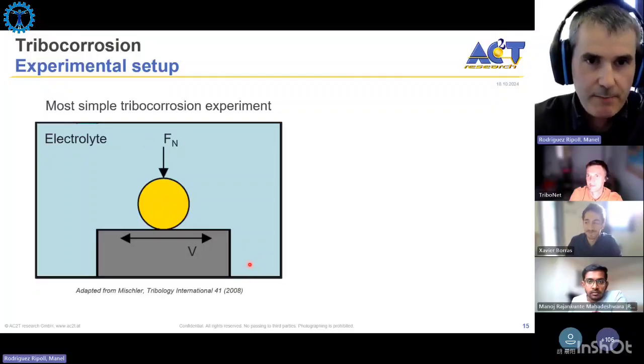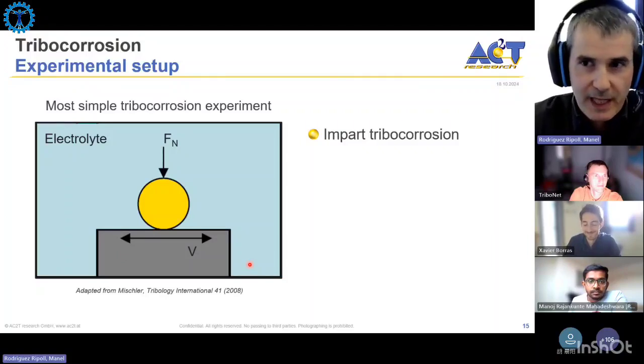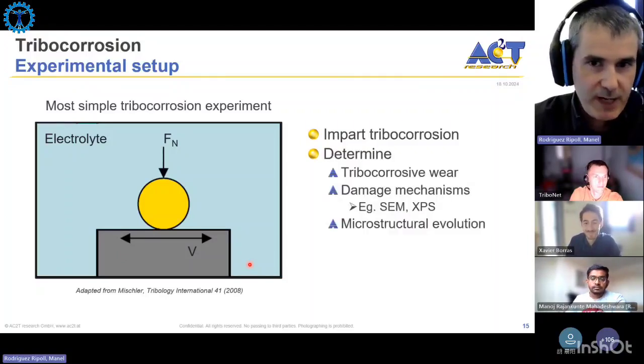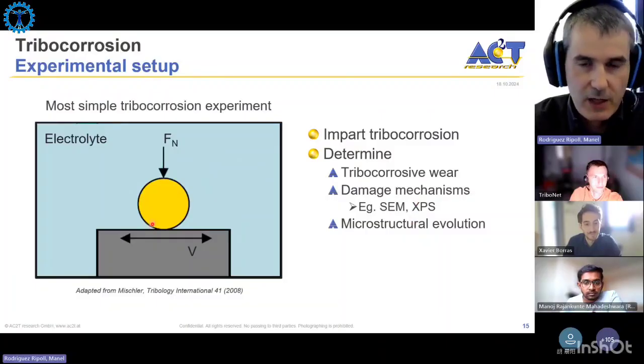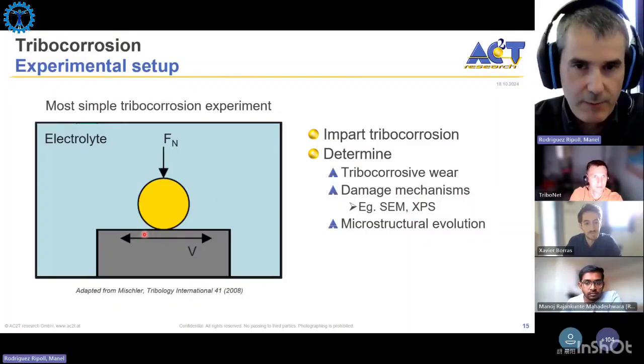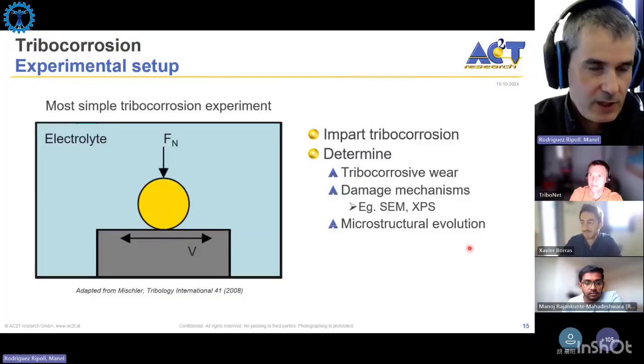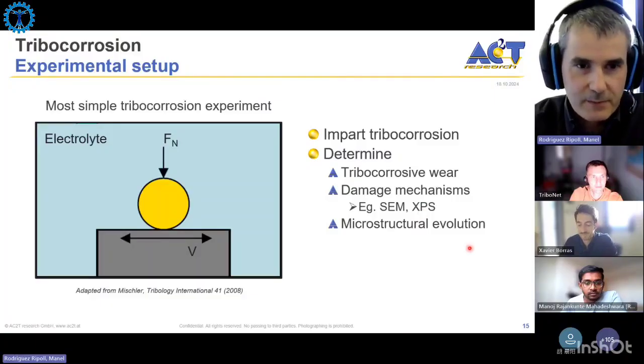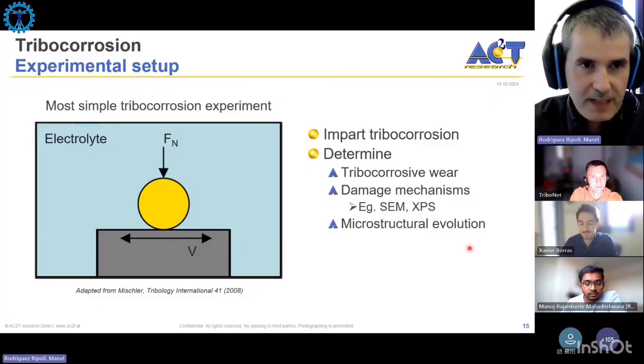By this we impart tribocorrosion, and at the end of the experiment we can see how much tribocorrosion wear there is. We can see the damage mechanism. We can see, for example, with SEM how the wear scar looks, and we can check with XPS how the chemistry of the wear scar looks compared to the unworn part. We can see how the microstructural evolution is occurring in the cross section. So we can really learn a lot of things, but still we cannot learn enough.